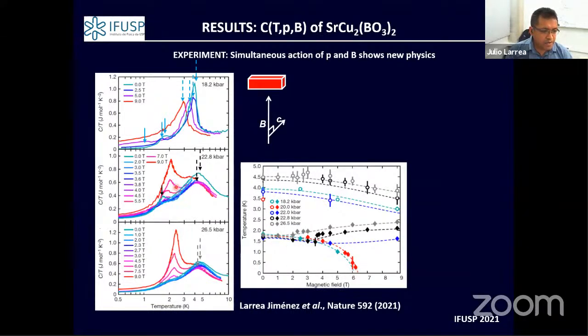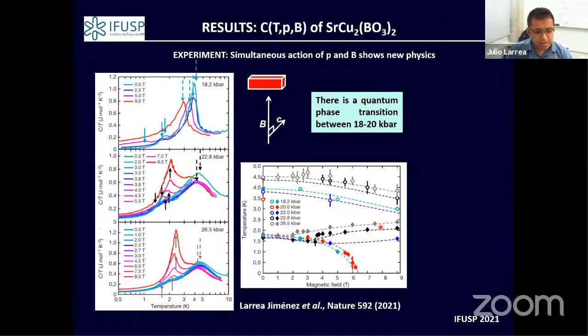And after, what we are doing is in higher pressure, we again see that the magnetic field for this small anomaly also decreases, but is not suppressed. Instead, it increases again, and it becomes more noticeable at the highest pressure, where it only increases. This is plotted here.